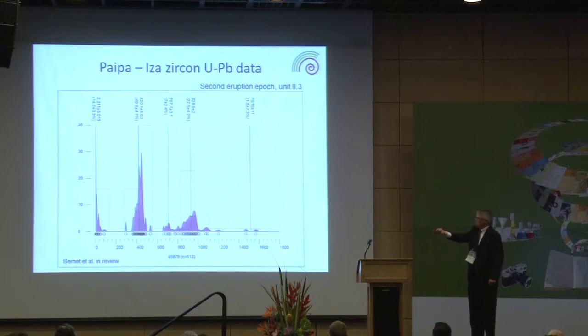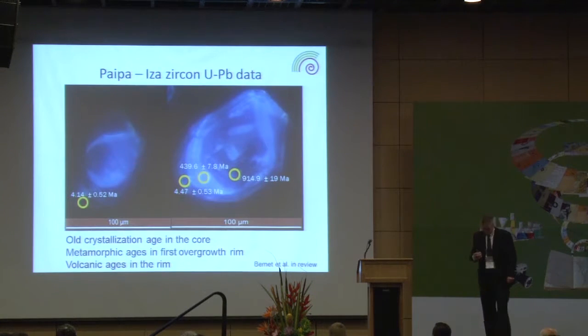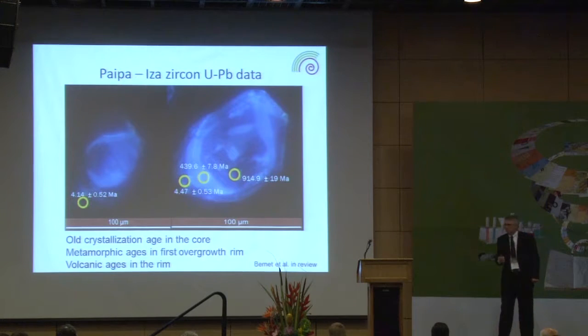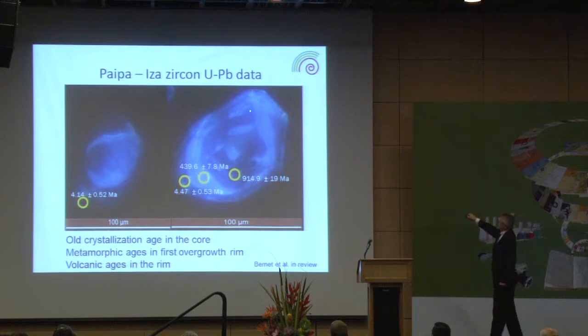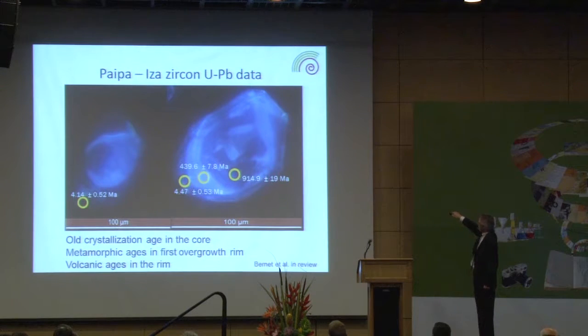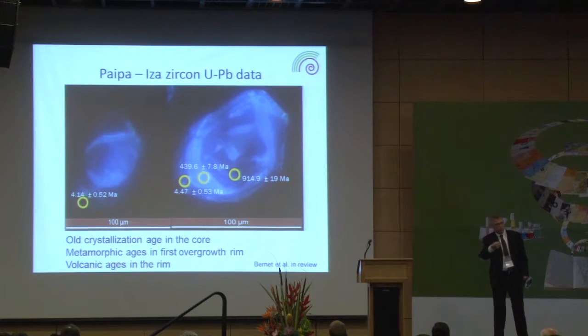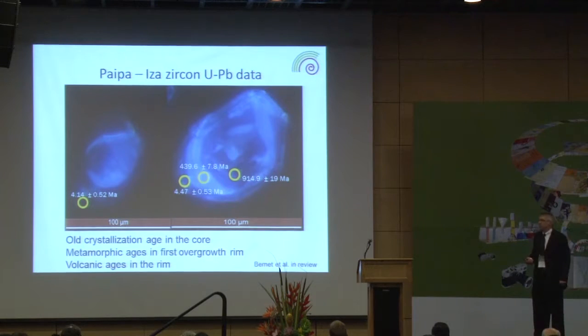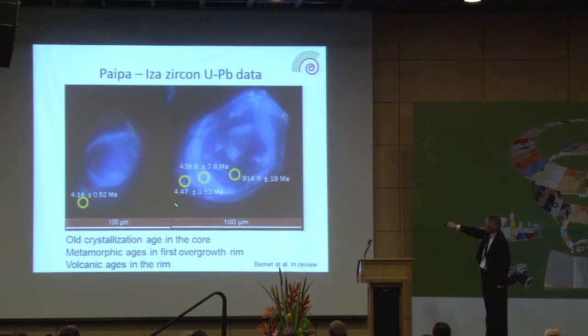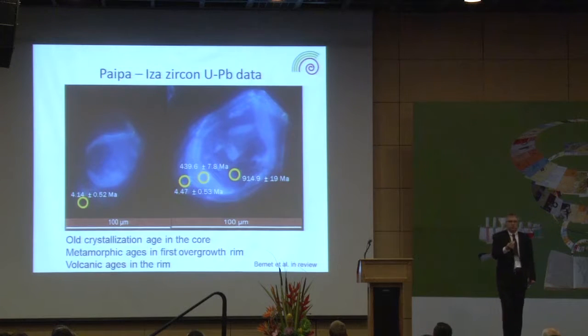But the interesting thing is, where do these ages come from, and we look at our zircons in detail, and this is where the cathodoluminescence analysis becomes very important. So we have, for example, this zircon here. We did 3 spot analyses on this grain, and we see the core is old, 900 million years. We have a metamorphic rim, about 440 million years, which corresponds to one of the metamorphic episodes in the area. And then we have this last euhedral overgrowth. It's a little bit difficult to see here, but this is where we actually get these volcanic ages. And it's only in the rims where we find these volcanic ages. It's not in the cores.